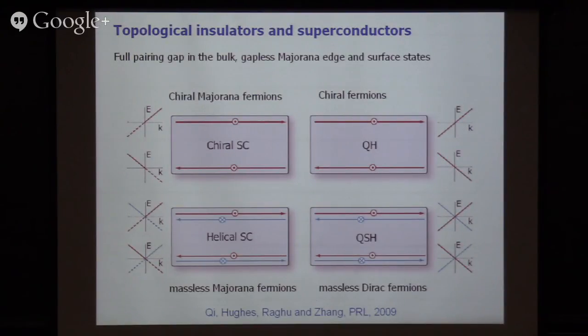So you may think this is already the smallest system you can have. I have one dimension, I don't have spin, I can only go in one direction. What can possibly be smaller than that? There's actually a duplication in this system, because this is after all an insulating state. So I fill the Fermi level up to E equals 0. All the negative energy states are filled, all the positive energy states are empty. But now I can take an electron from E less than 0 to E greater than 0, so I can have two charge types. I can have particle type and hole type. And that is actually a duplication which you can, in principle, eliminate.